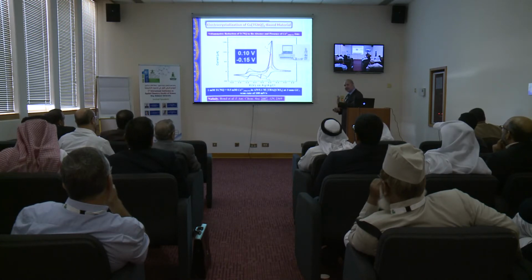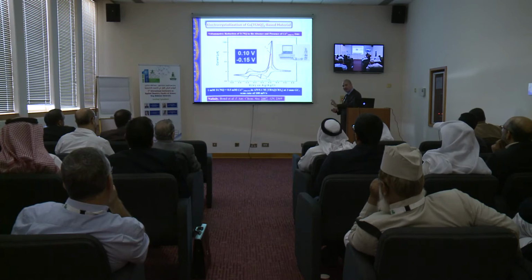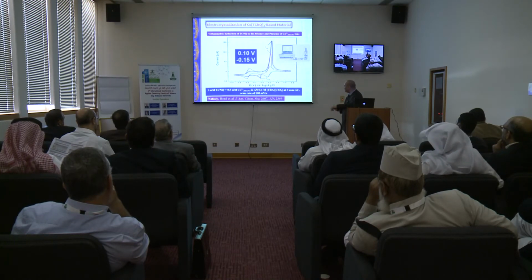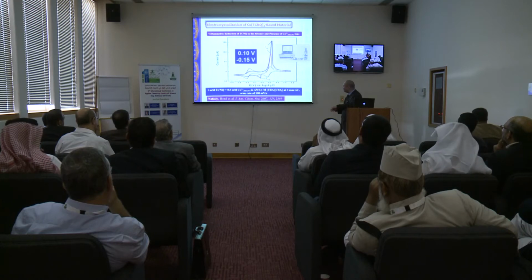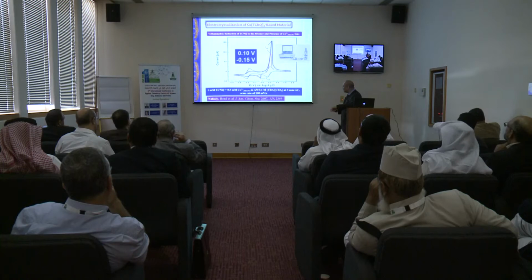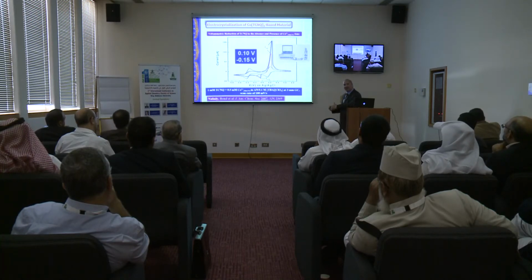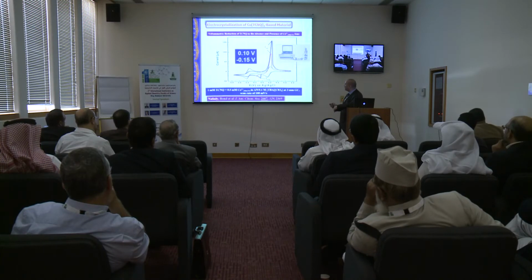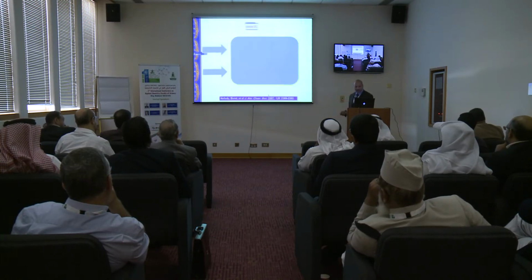That indicates that the monoanion and the dianion that you are forming are stable, at least on the CV time scale. However, when you add any metal cation like cobalt, nickel, and so on, you can see there is a massive change in the voltammogram. The black one is now going to the blue one. That sharp increase in current is consistent with depositing a new material at the electrode surface, and this material is basically the cobalt TCNQ that we are forming.